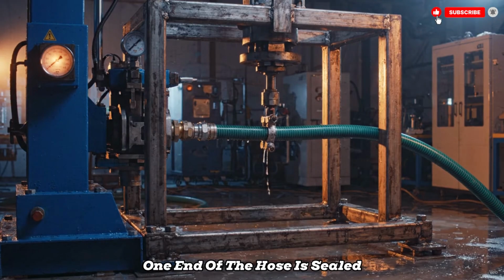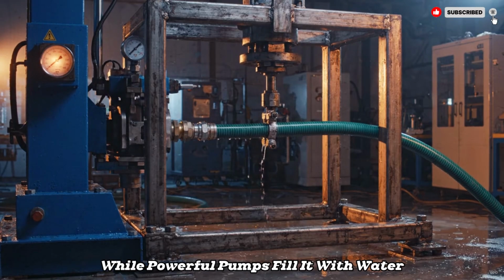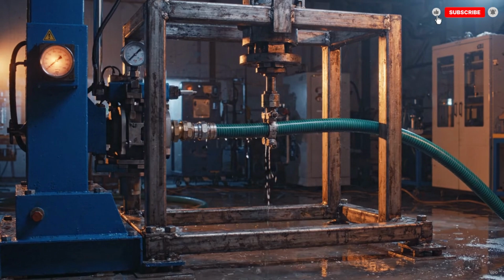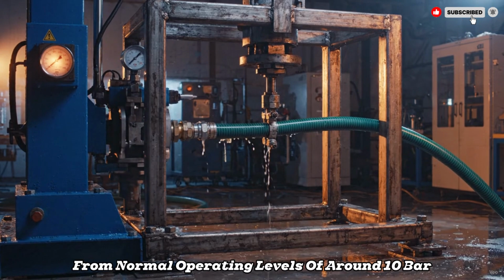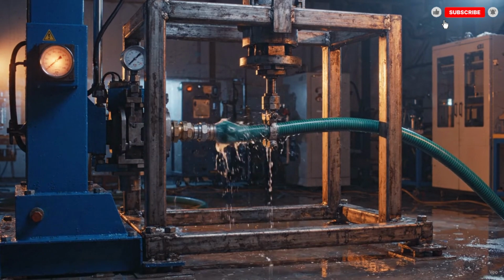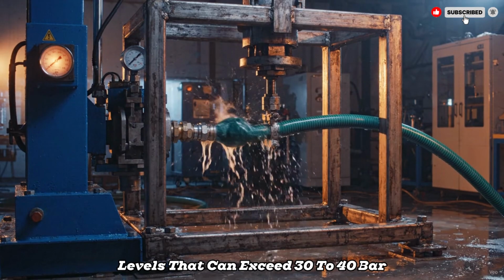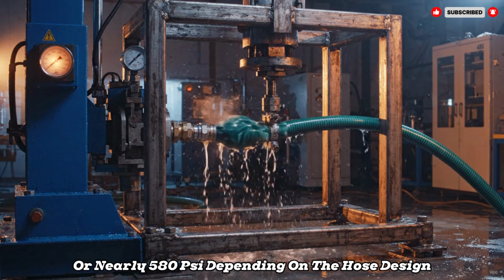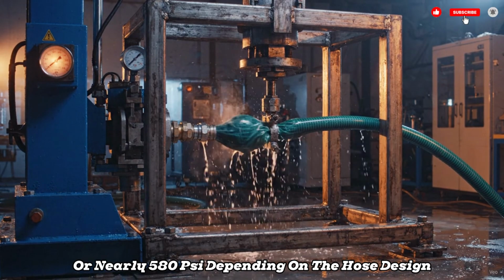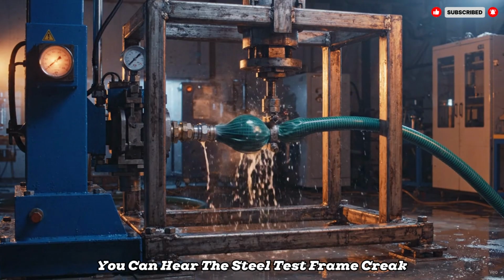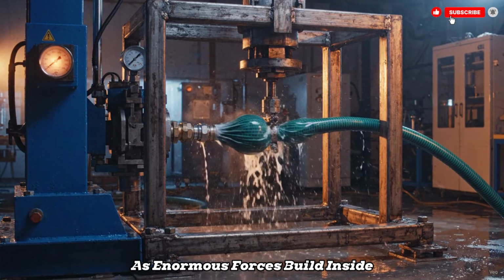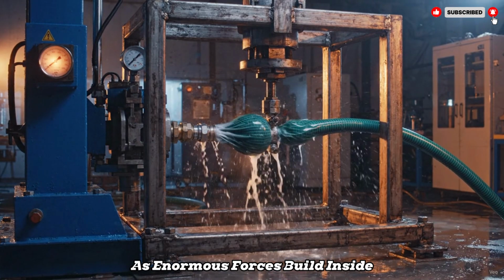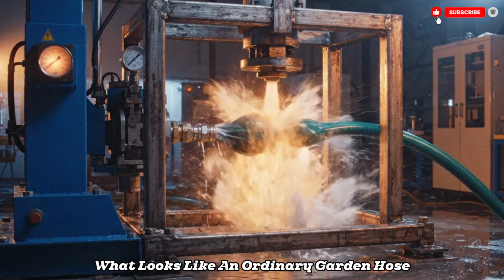Now comes the test every engineer respects. One end of the hose is sealed while powerful pumps fill it with water under controlled conditions. Pressure climbs steadily from normal operating levels of around 10 bar to extreme burst test levels that can exceed 30 to 40 bar, or nearly 580 psi, depending on the hose design. You can hear the steel test frame creak as enormous forces build inside what looks like an ordinary garden hose.